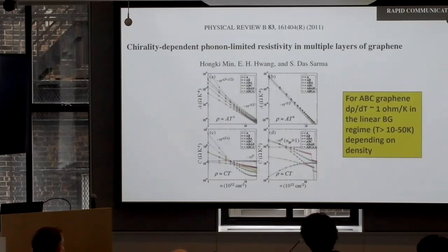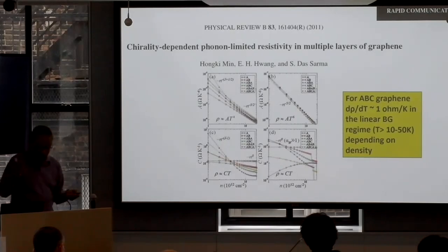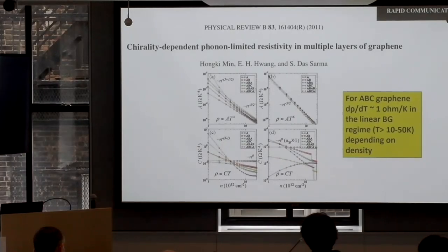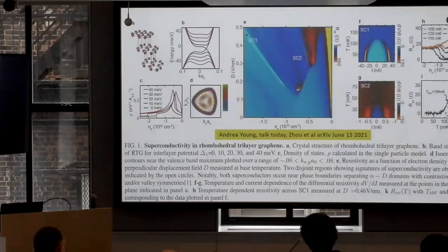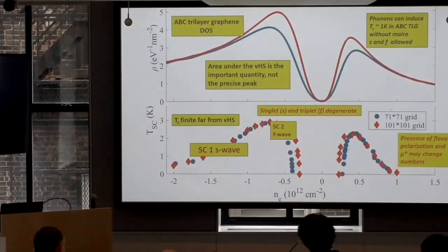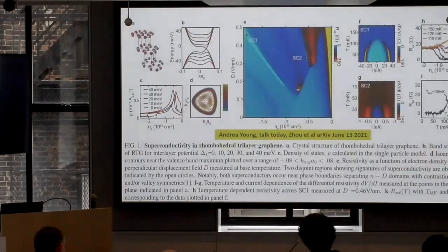So a long time ago, we pointed out for graphene, we originally did monolayer, but you can have multilayer graphene, and you can calculate now, and d rho dT is 1 ohm per Kelvin, because again, it's very small, because the electron-phonon coupling is very weak. We calculate for all these different materials. Our prediction, and this is a very important point, everybody should pay attention, is that there should be a linear resistivity in this system, if it's phonons, at some temperature.